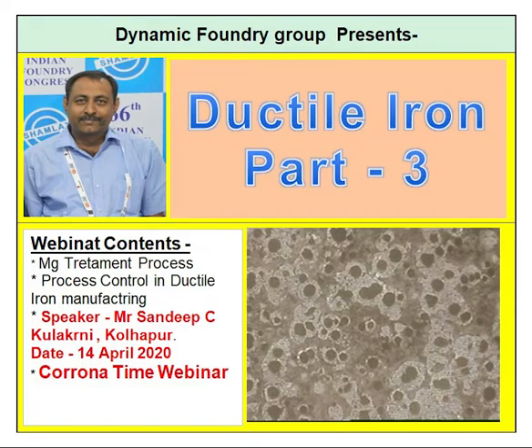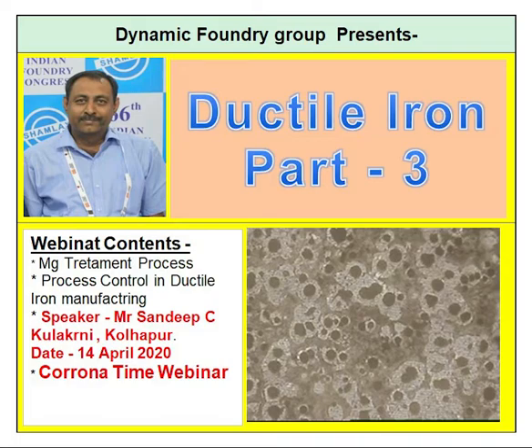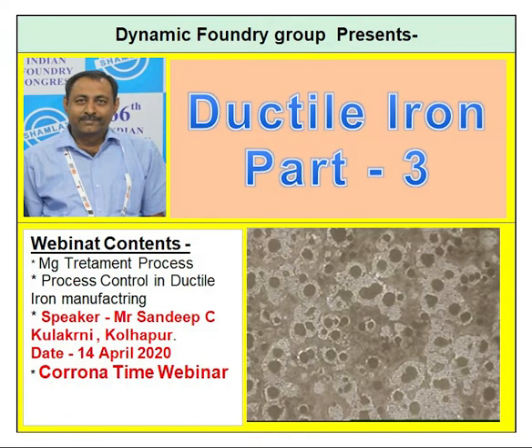Tapping time is very important. Deslagging of the metal is very important. Deslagging helps you in reducing temperature loss as well as preventing slag from going along with the metal inside the casting, so casting soundness will be affected by slag and dross. Dross is continuously generated in ductile iron because magnesium is present, and magnesium will try to form magnesium oxides and magnesium sulfides.